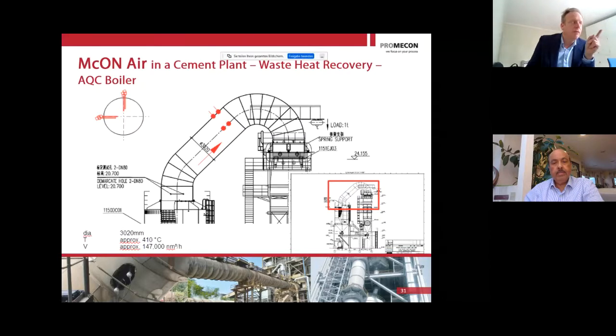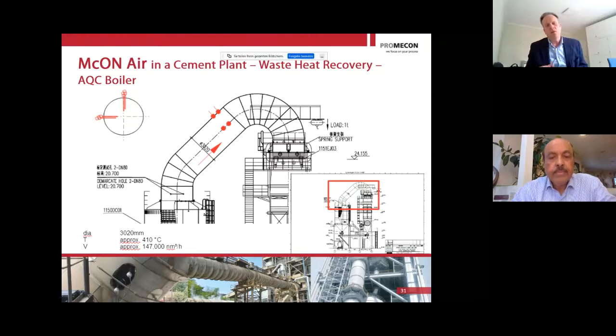In this case, we have 2 pairs of sensors installed instead of just 1 pair. And that is in order to better balance the stratification that we see in the duct. And as a result, again, we have a very reliable drift-free measurement of flow and, combined with temperature, of enthalpy into our waste heat recovery system.